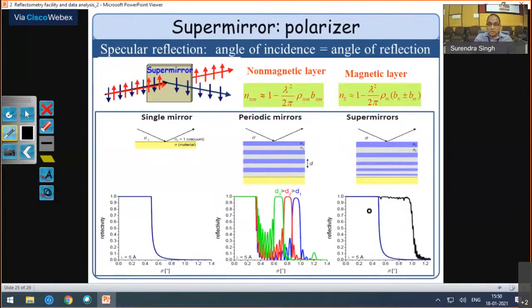So your theta c is also extending, because all this overlap gives you higher reflectivity. A single layer has a certain theta c, but when you make a periodic multilayer where the Bragg peaks overlap, you are essentially extending theta c further, up to a higher value.